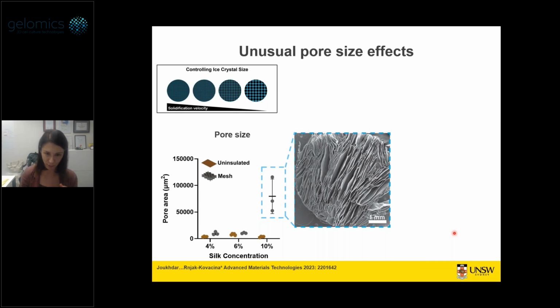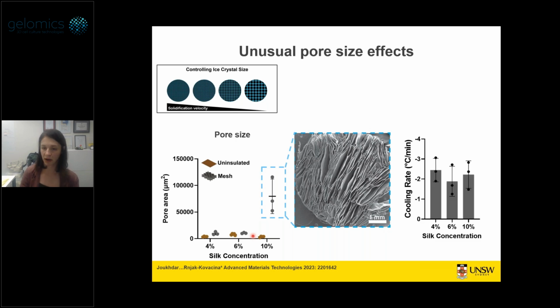But during this process, when we were studying this freezing, we noticed an interesting thing. Bear with me for a second because it's a bit of an unusual story, and I'll get back to hydrogels. It's related. So normally, as I said, if you slow down freezing, you get larger pores, and we're indeed seeing this. This is the pore area here. This is the silk concentration of different silks. And with the mesh insulator, we can slow down freezing. So each time if we slow down freezing, we see larger pores. But at 10% silk concentration, we're seeing these absolutely huge pores. Very, very surprising relative to 4 and 6% silk, and yet the cooling rate, the freezing rate of these is the same. So it's not related to this well-known process of slowing down freezing.